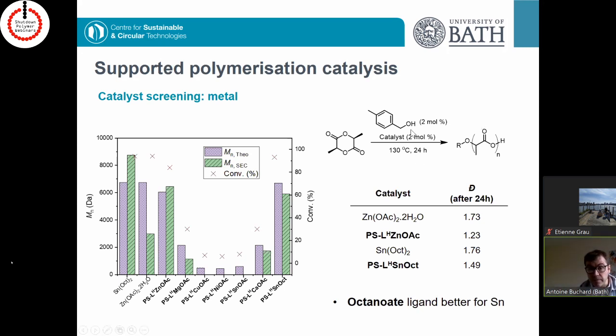Note that at the same time, we used a co-initiator, so a benzyl alcohol derivative. We used the methyl one because it's a solid and it's quite easy to recrystallize and to weigh. And we used this combination to test the activity in the lactide polymerization. And we compared those results with the gold standard in industry right now, which is tin octanoate, a viscous liquid, which is used for the homogeneous polymerization.